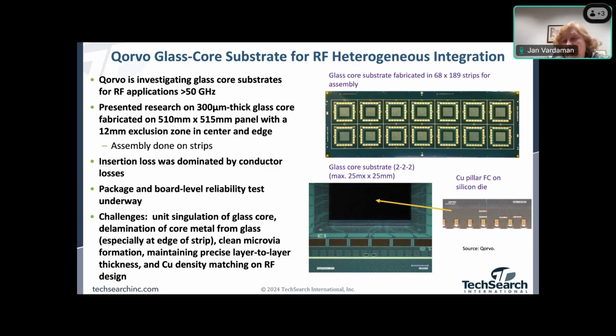Now, some of the challenges they've encountered are things like unit singulation of the glass core, delamination of the core metal from the glass, especially at that strip edge, clean microvia formation, maintaining a precise layer-to-layer thickness, and copper density matching on the RF design. And they're still continuing this research with the company that they're working with. Next slide, please.